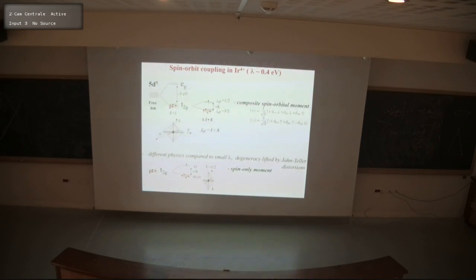The conventional mechanism, if we ignore spin-orbit coupling, is to look at local lattice distortions and imagine that this octahedron now elongates along the z-axis. Then the orbitals that have a z-axis component become low energy compared to the dxy orbital, which is all in the xy plane. If we put all our 5 electrons in here, we gain energy compared to the undistorted case. This is the basis of the Jahn-Teller effect, which tells us the orbital degeneracy is unstable and will ultimately be lifted by lattice distortions, which, even though they cost some energy that is quadratic in the displacement, give an electronic energy gain that is linear.